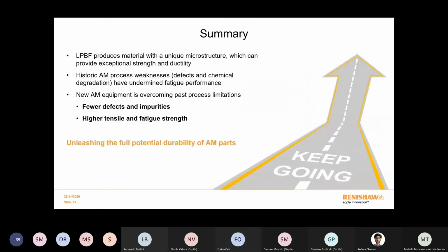So I'm slightly exceeding my time, but I'm just summarizing that laser powder bed fusion is a process that has, as a result, a unique, fantastic thin microstructure. It can provide very high performance in terms of tensile strength and elongation if it's done properly. And there is a lot of work to do on fatigue, which is good news for the research in the university, because that will greatly affect the possibility to apply additive manufacturing to a lot of processes in the future, especially in the aerospace and automotive industry.